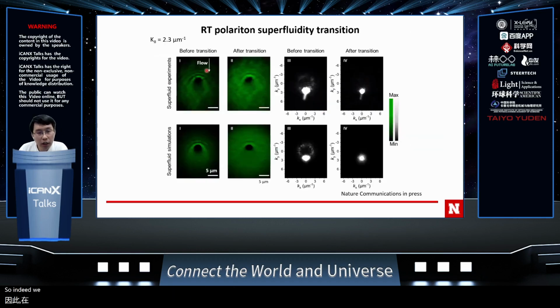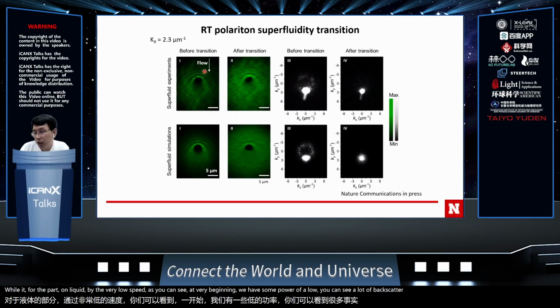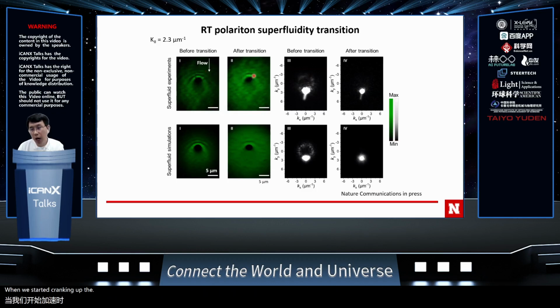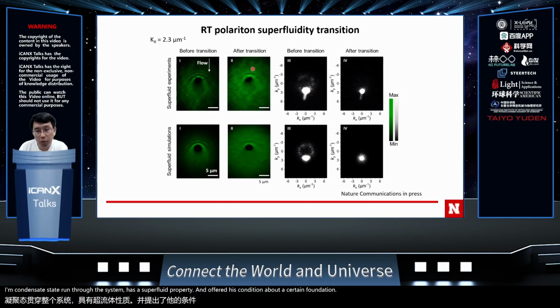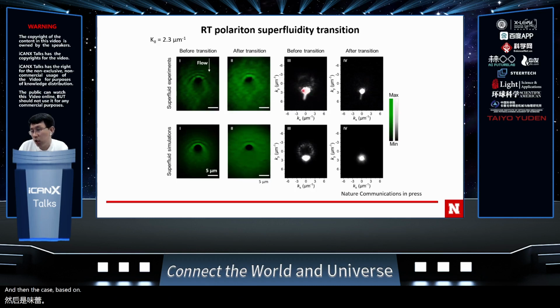So indeed, we did the experiments. When we flow the polariton liquid at a very low speed, at the very beginning with very low pump power, you can see a lot of backscattering. When we start cranking up the laser power, we enter the Bose-Einstein condensate state, and this BEC state gives the system superfluidity. After this transition above a certain pump laser threshold, we see the backscattering become fully diminished. The K-space also supports the discovery: the backscattering we observe at the very beginning is later fully suppressed, which is quite exciting.